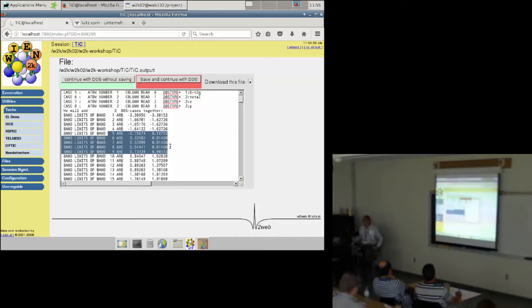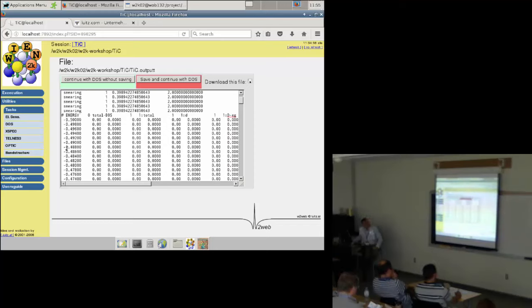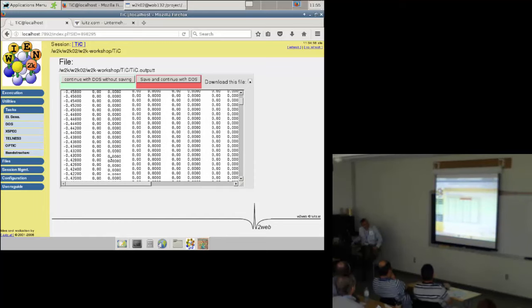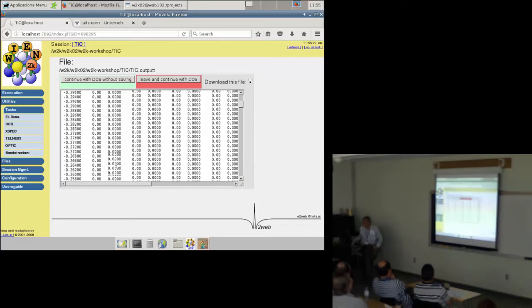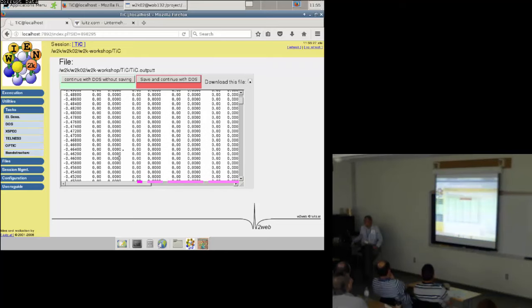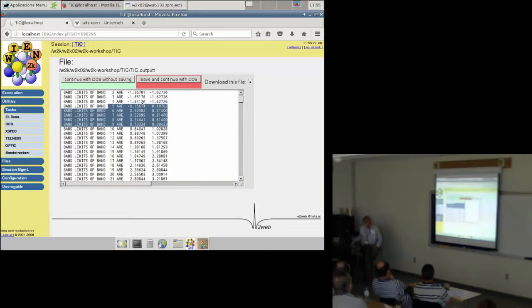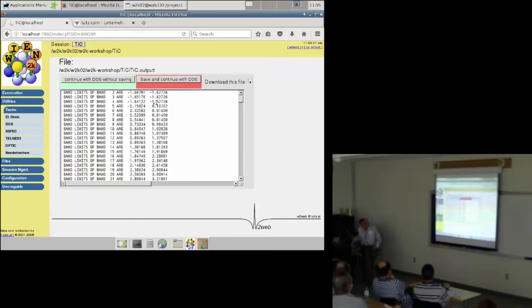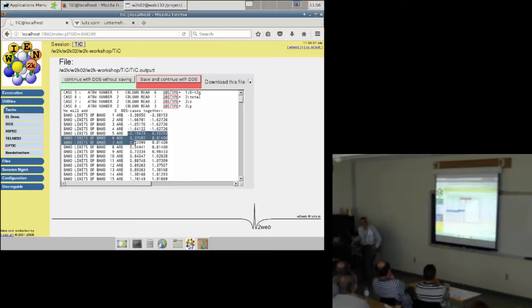Now with the density of states we can analyze the electronic structure. At the bottom of the output you see a listing of energy, total DOS, and on the side the integral of the total DOS. There is no density of states below the energy minimum we set at -0.5 Rydberg, which makes sense because there is a large gap between -1.6 and -0.15 Rydberg — so we are not plotting the core states. The DOS starts around -0.1 Rydberg, and on the integral side you see the analytical integrals — don't integrate the DOS yourself numerically, as this is very inaccurate.